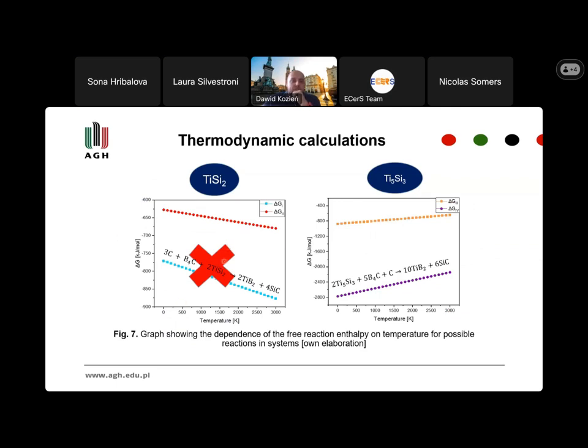This reaction should not ever exist according to the information that we obtained from a lot of articles, but it exists, as our results showed. For energy reasons, the reaction is more favorable, leading to the formation of products such as titanium carbide, titanium diboride, and silicon carbide. Thus the expected products of reaction sintering in the mixture of starting powders are a composite consisting of these chemical compounds. In the case of the other reaction taking place in the system, only titanium diboride with silicon carbide was formed.